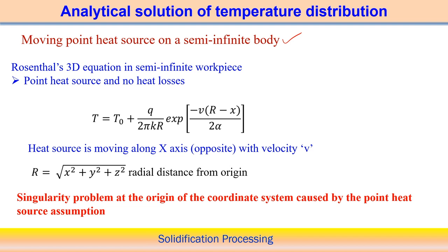So assuming the point heat source is one assumption, and there are no heat losses from the boundary of the welding plate, because we assume a semi infinite body. With these two assumptions we reach this particular solution: T equals T0 plus Q, the total heat applied, over thermal conductivity, where R is the radial distance from the origin, a variable here, V is the welding velocity, and this is the exponential e to the power minus V (R minus x) by 2 alpha. Alpha we already defined as the thermal diffusivity for a particular material. If you observe carefully, with the assumptions of the point heat source and no heat loss from the boundary, we get this temperature distribution.